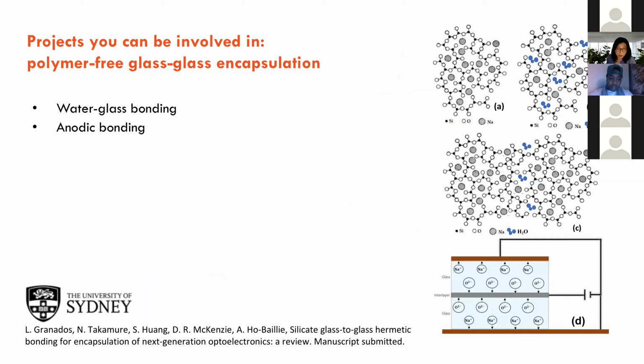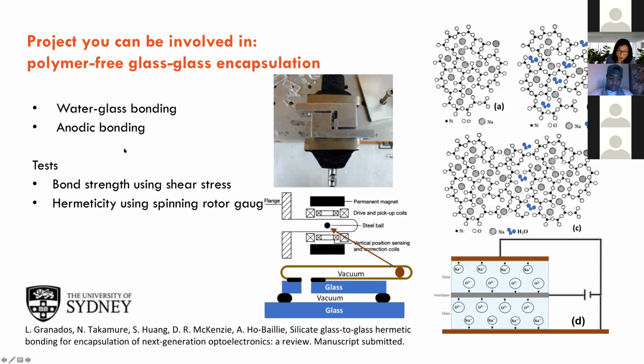So perhaps we can look at polymer-free glass encapsulation. This is in partnership with David McKenzie and the School of Physics, because they've got quite a lot of experience with glass. We look at whether we can use water glass or anodic bonding for low temperature bonding, and we can do it without the polymer. So projects you can be involved in are to look at the merit of these bonding techniques, look at the bond strengths, carry out some shear stress tests, and also look at the hermeticity by using this thing called the spinning rotor gauge. Basically, the more hermetic the joint is, the tighter the joint is, this unit will be able to hold vacuum, and this ball will be able to spin very fast. So the hermeticity is proportional to the speed of the spinning ball.